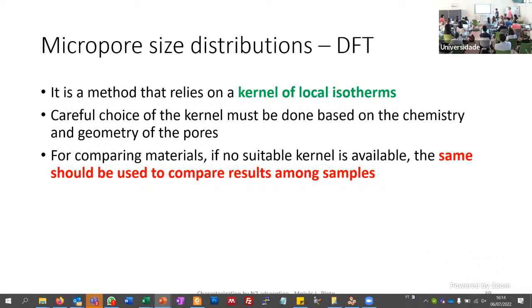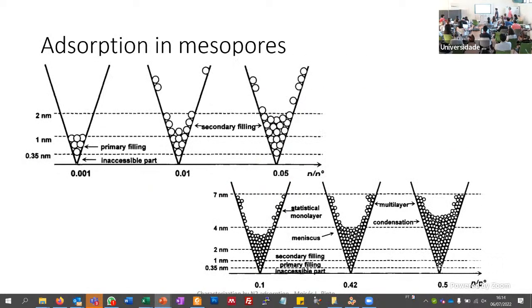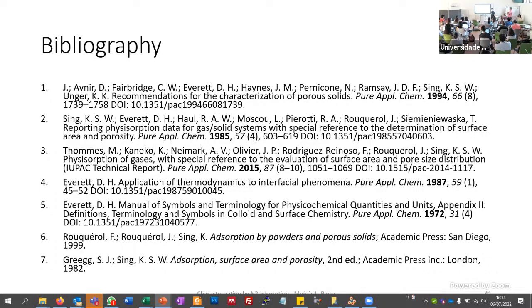Yes? So actually these methods can help you to analyze the pore sizes from very narrow pores up to very wide pores. These methods are good because they are not just applied to the initial part of the isotherm, but for the full isotherm, because you are comparing your isotherm against a set of kernel of isotherms. If you have these theoretical isotherms on the mesopores part, you can also extend this. I give you here a set of books and texts that you can read, and then I'm going to pass to Richard that is going to talk about the.